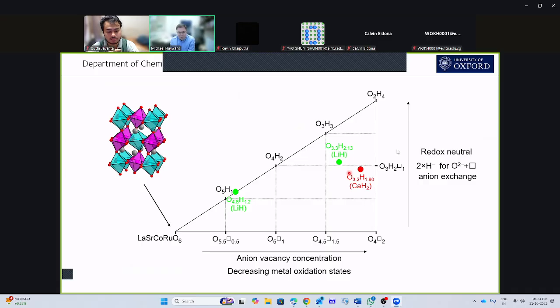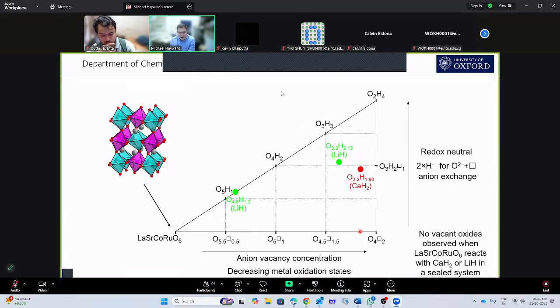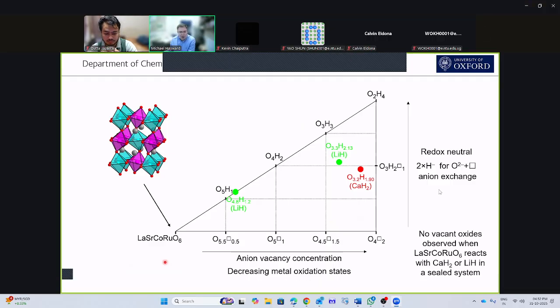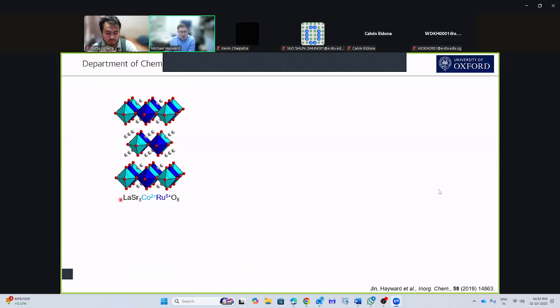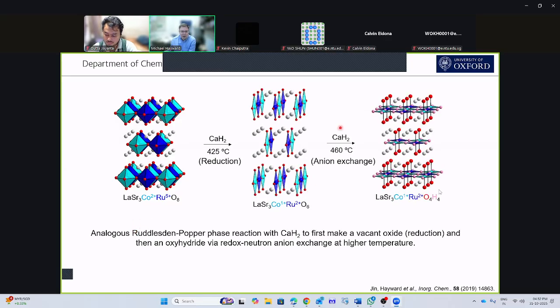But what we find from doing those reactions is we don't see any vacant oxides. There are no phases that we've made down here, which is a bit surprising because what I can do is take the equivalent Ruddlesden-Popper phase. So now we've got cobalt and ruthenium in the same oxidation states as the perovskite, but I've made a layered compound. And if I do the reaction here, what I find is I can make an oxyhydride, but I go via an identifiable intermediate, which is the reduced oxygen deficient phase.